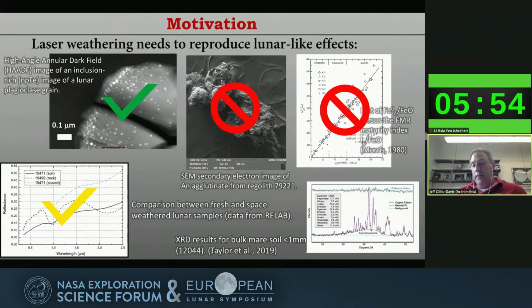And then on the lower right, there's XRD analysis from a paper by Taylor et al. in 2019, in which minerals show good peaks that are related to elements in different mineral lattices. And for lunar regolith, where there are a lot of agglutinates, there's this amorphous hump that you can see on the very low part. It doesn't have Bragg scattering because it's just elements in a glass. So it's another criterion which we need to be able to recreate with laser space weathering, but we don't.